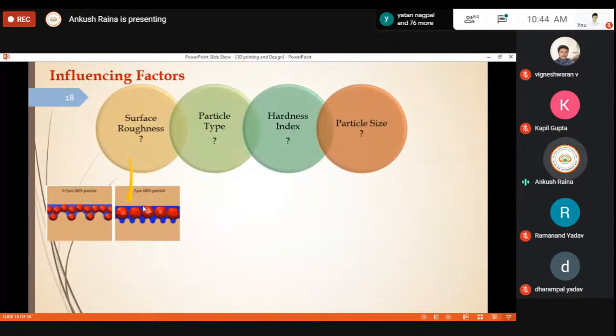You can see over here, we have the different nanoparticles that are being used. In the first image, you can see the surface roughness is more, and in the second image, the surface roughness is less, although it also has a relation with the particles. If the surface is smooth, there will be less friction. But in the first image, there are particles embedding in the surface, and certainly that also plays an important role in governing the friction and wear properties.